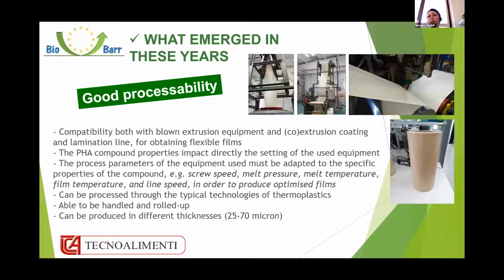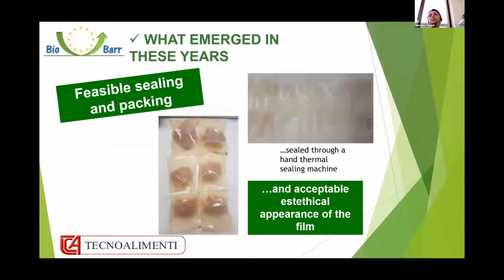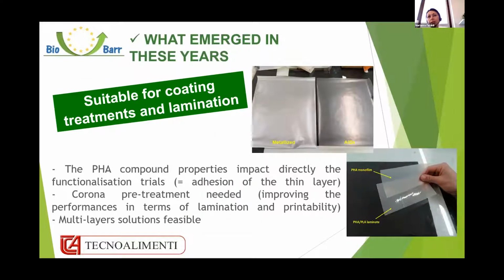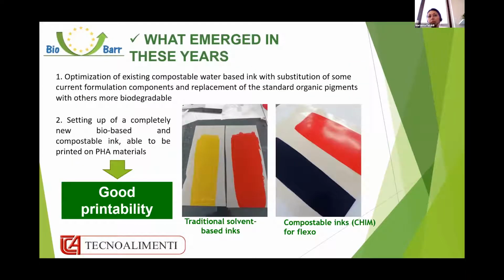It can be processed through the typical technologies of thermoplastics. It is able to be handled and rolled up and can be produced in different thicknesses. It is sealed and can be packed with an acceptable aesthetical appearance of the film. It is possible to look through even if it is not completely transparent. It is still a little bit milky. It is suitable for coating treatments and lamination, with or without corona pretreatment, this is something we are still investigating, and multi-layer solutions are feasible. Good printability, so the new inks developed inside BioBarr can be printed on the PHA materials.